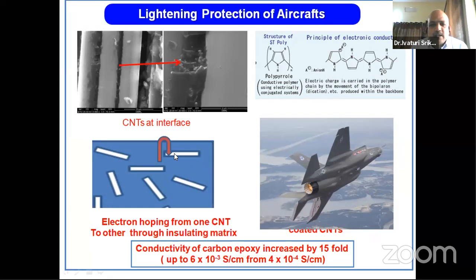So you need to impart or increase the conductivity of composites. So we have done some work on that. If it is a conventional composite, what is shown here, this is a carbon fiber filament, this is a matrix. In case of a conventional composite, this matrix is insulating. The matrix is a polymer which is insulating, which finally reduces the conductivity. If you add nanomaterials, you can see here, the nanomaterials are bridging between two carbons and thus ensuring continuity in the conductivity. This is a nanomaterial, a typical image, showing how the electron hopping can happen.